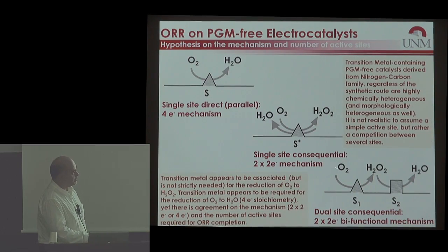The 2x2 mechanism can be of two types. One with two chemically different active sites. So it's a 2x2 mechanism of reduction of oxygen when peroxide is formed and has to travel between the first site and the second. This is a little bit of a simplification because there could be a third site that can heterogeneously decompose hydrogen peroxide, especially in acid, that is not electrochemical. So you can lose hydrogen peroxide and you can create oxygen locally by chemical decomposition.